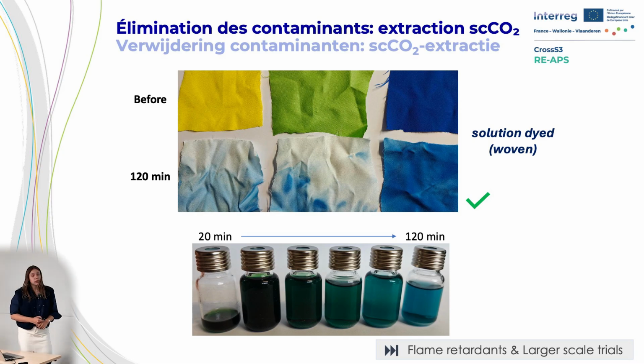All are woven solution dyed textiles with the same extraction parameters that we used before. And the yellow and the green one are quite good. Yeah, the color is removed, but for the blue one it is still not completely removed. I have to say that all materials were in the same trial, so probably the bluish ink that you see over here comes from the blue one that was in the same trial.